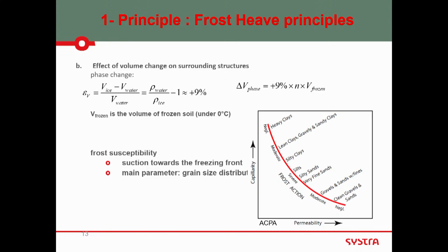And this unsaturation comes with capillarity also. So the water, in fact, you can imagine this area as being very small tubes, like when we were at university doing experiments on capillarity. Very small tubes where water is going up naturally. It's a function of the contact between the tube, if the tube is clean or not clean, and the water. And also the type of water, if it's contaminated or not contaminated, and so on. So these are capillarity forces.